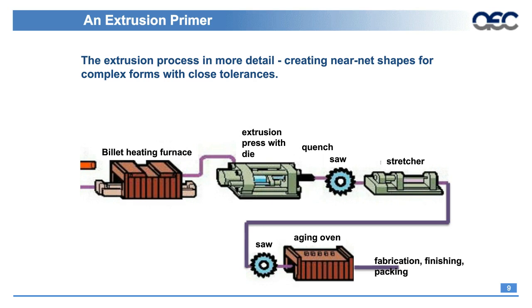So in this particular instance, you see a very basic diagram of most of the extrusion process. There is some additional ancillary equipment towards the end if we're looking at packing and doing things like that. But the actual production of the extrusion itself, we start by preheating the billet before it goes into the extrusion press. So we'll preheat the billet. We'll present the billet to the extrusion press. We will press the billet through the die, and that will run out basically down the table that sits in front of the extrusion press, and then we'll do a hot sawing operation where we'll cut that long extrusion to a piece then that moves transversely to a stretching system where we'll straighten it, and then a finish saw operation where we'll cut it to basically a rough cut length.